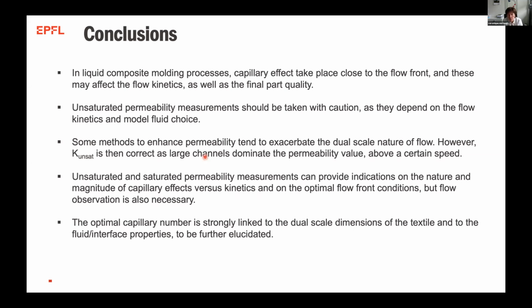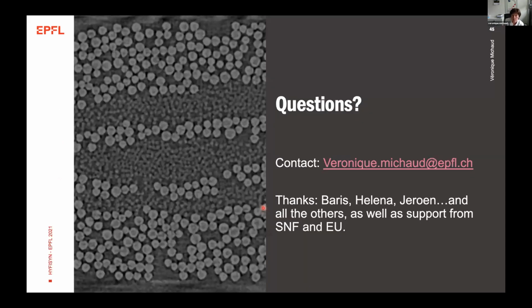Unsaturated and saturated permeability measurements can provide indications on the nature and the magnitude of these capillary effects. So we're not completely helpless. There are ways to measure these effects, either by doing pressure measurements like I showed, or by doing flow front observation, or by doing both, which is also possible. And then the optimal capillary number is linked to the dual scale dimensions of the textile and to the fluid interface properties. So what is this optimal capillary number is something that everybody measured. We know for a normal fabric, it's close to 0.01 or something like that. And it's to be further elucidated really to find how this capillary number evolves with the textile dimensions and the interface properties. And with this, I will stop.